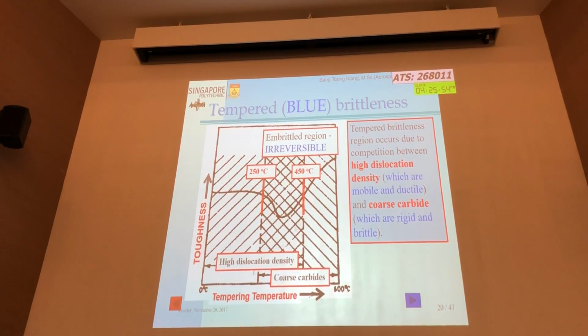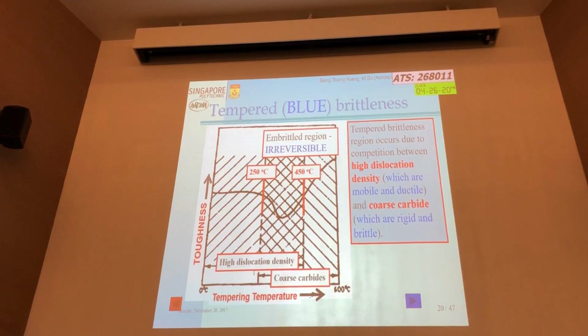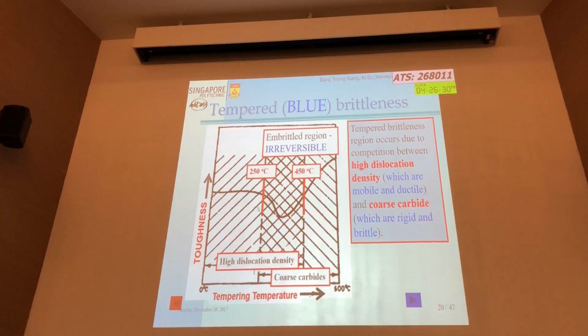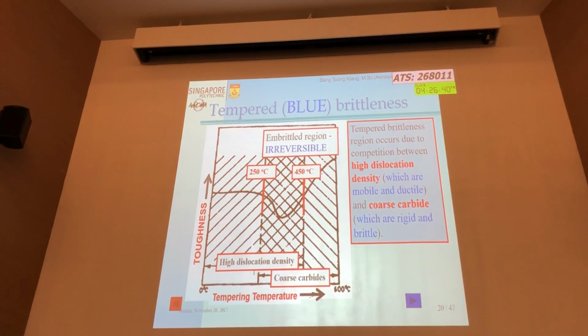But at this point the atoms try to move at the same time as the carbide. So take note that the carbide starts to form, and the carbide attempts to migrate itself. But at this particular junction, between these temperatures, these two migrating species interact. One is trying to go there, the other is stopping it. You got what I mean? So this interaction generates the temper brittleness. So remember the carbide is formed in the grain and tends to move to the grain boundary during tempering.